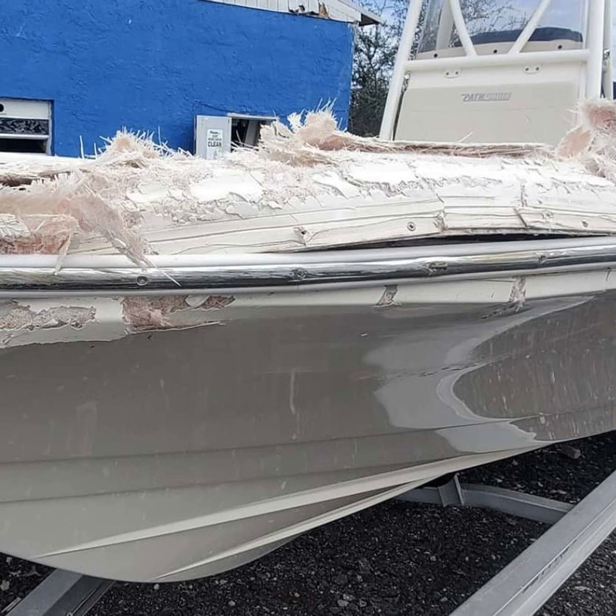If you screw something down or you make a hole in the deck or something like that, and you don't seal it properly, and over time, water has a chance to seep into those holes, the balsa just absorbs it like a dish sponge. It's not a good situation. And so very, very frequently, I've seen core failures where someone will bring a boat that has a soft spot in the deck or multiple soft spots. And that is often due to wet balsa. And that can happen on the hull too. There's some hulls out there that are cored with balsa.